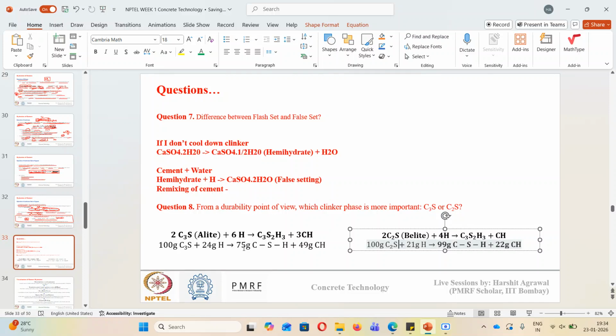However, from strength point of view, C3S is more important for early strength gain. Why? Because C3S reacts readily, while C2S takes time to react. So if we want early strength, we need more proportion of C3S in a cement.